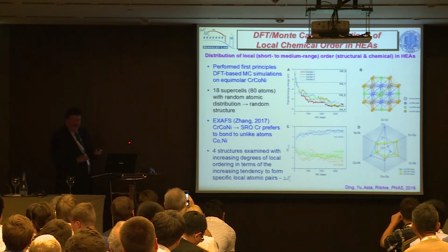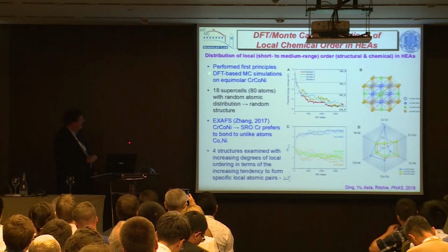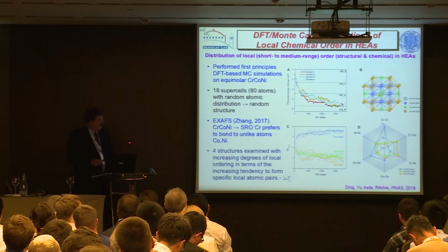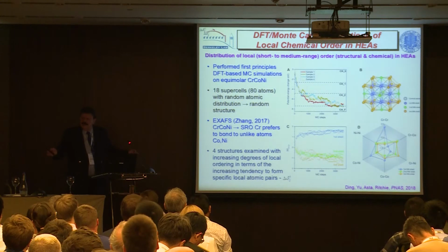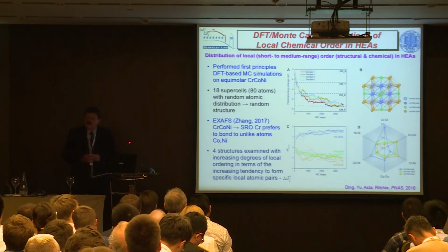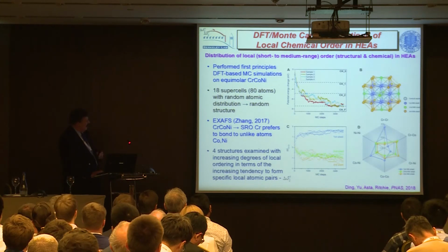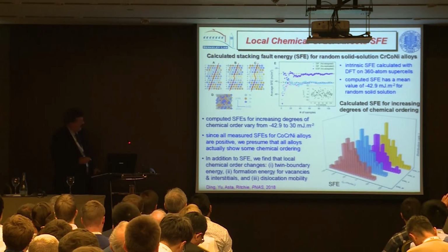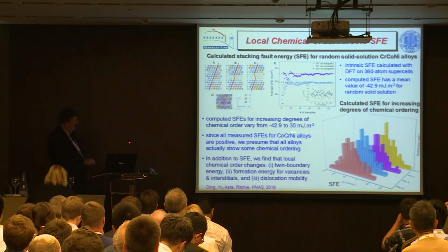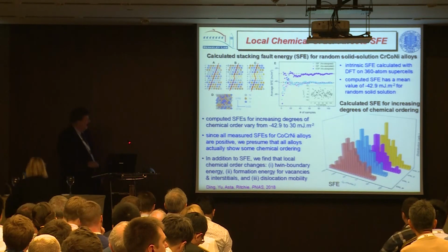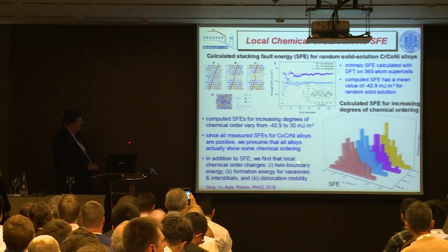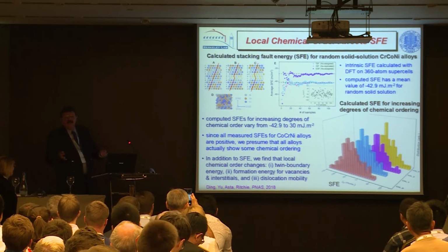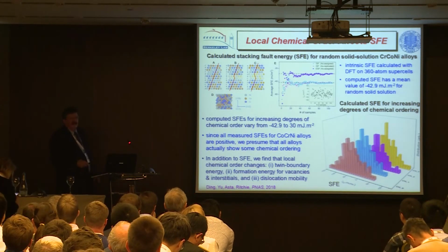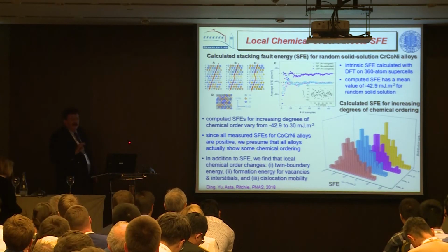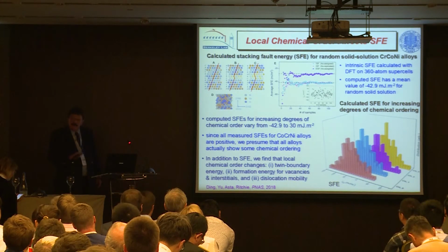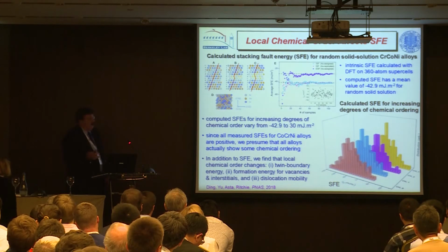We've done a number of calculations, again, this is all in the realm of DFT or MD. We've done Monte Carlo DFT simulations where we've taken a random solid solution for these alloys and then started to put increasing degrees of local order in. And what we find is that there's a dramatic effect on things like the stacking energy. Stacking energy can vary by up to 70 millijoules per meter squared, with a change in the twin boundary energies, and a change in the energies for interstitial formation. So we think also that local order has a big effect in these alloys too. No one's seen it yet, very little evidence, but we think that's important too.